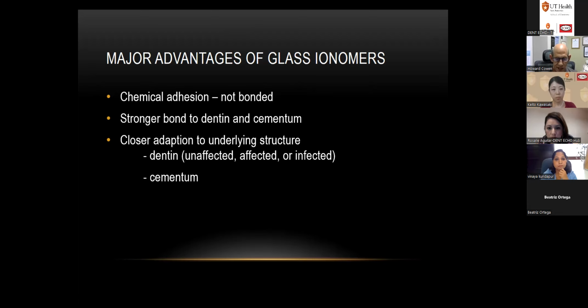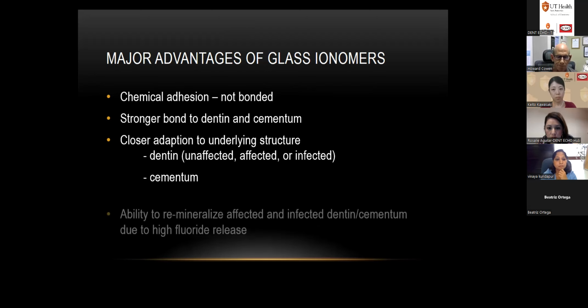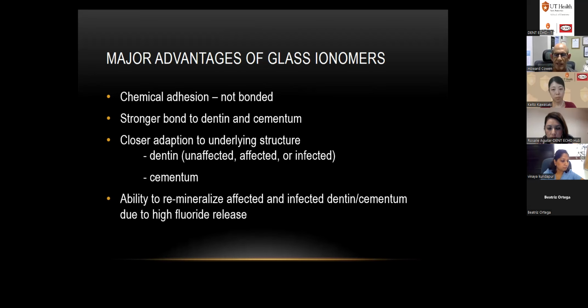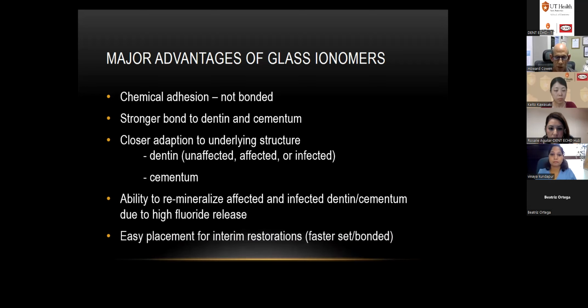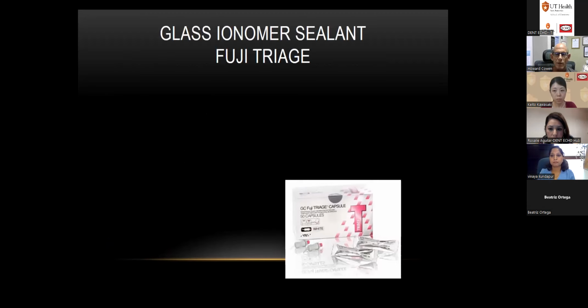Chemical adhesion also has a closer adaptation to dentin and cementum, whether the dentin is unaffected, affected, or infected, and it has the ability to remineralize the affected and infected dentin due to high fluoride release. So putting these materials on affected dentin effectively hardens that dentin. With the stepwise method of going back in, as they kept going back, they found that the material was hardened. And so that's why partial caries removal turned into more of a permanent procedure instead of a transitional two-step procedure. Easy placement of these materials is also a major advantage.